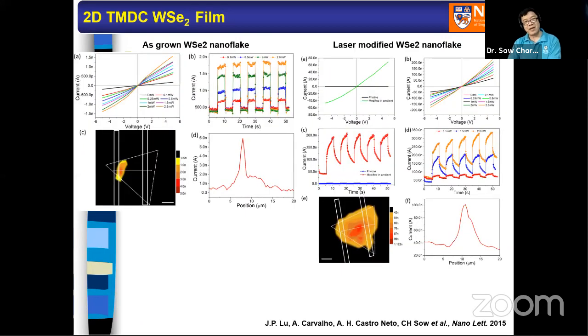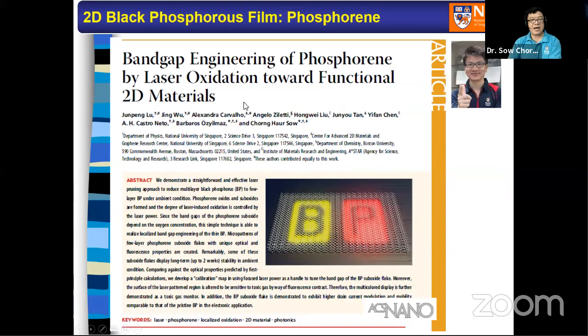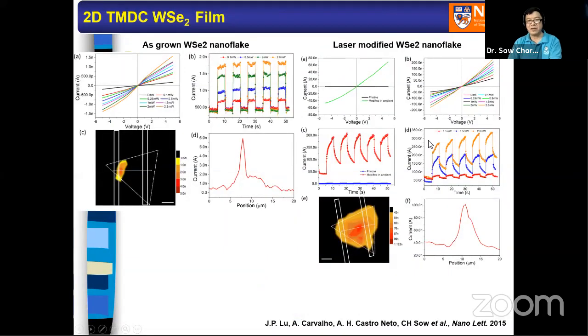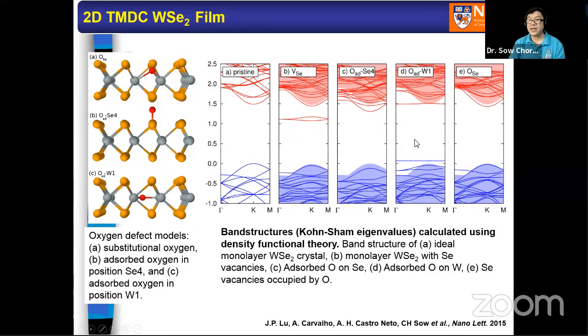And again, we do photocurrent measurement. Before modification, the photoresponse goes up by about 4 times. But after modification, it goes up by about a few hundred times. So it's very good. The nice thing is that we have a lot of colleagues in NUS who are very good at DFT, density functional theory calculation, so we always approach them. This is a team led by Dr. Alexandra Carvalho and Professor Antonio Castro Neto.